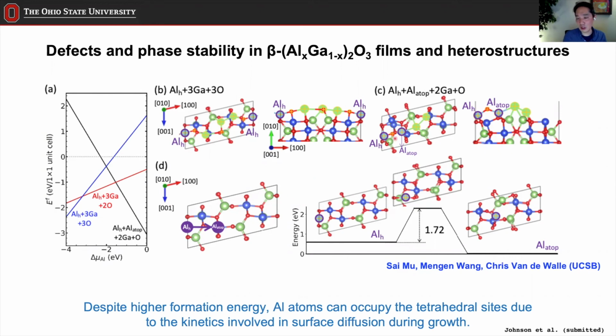I actually don't know all the details, so I won't explain all the details. But the simulation results confirm that because the process is controlled by the kinetics of the surface diffusion, it is likely that some of the aluminum atoms can end up at the tetrahedral site, even though the energy level is higher at that site as compared to the octahedral site.